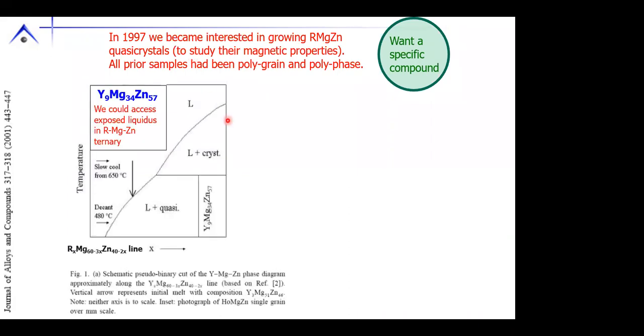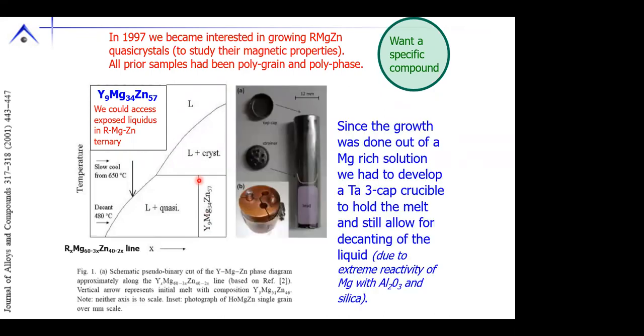Now, we were able to access an exposed liquidus surface to grow these. So we could cool down a melt rich in magnesium and zinc and intersect this liquidus for growing the quasicrystalline phase. We were able to refine this phase diagram. Now, what this required, though, was us to work with a solution that's rich in magnesium, which means that we had to change from using alumina and silica to tantalum and develop a way of straining and decanting tantalum growths.